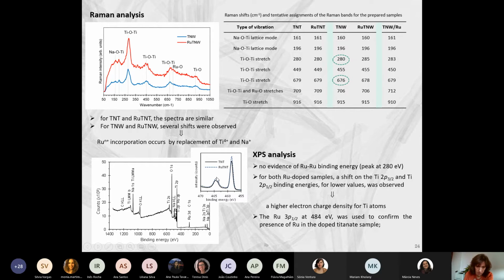Sorry, it's not very visible. We have a shift in these peaks that tell us that we have a difference in the density of charge surrounding the titanium atoms. And this is associated with the presence of some ruthenium replacing titanium. And we had these results for nanotubes and also for nanowires. So we have ruthenium replacing some titanium. Of course, we have confirmed the presence of ruthenium in our samples.